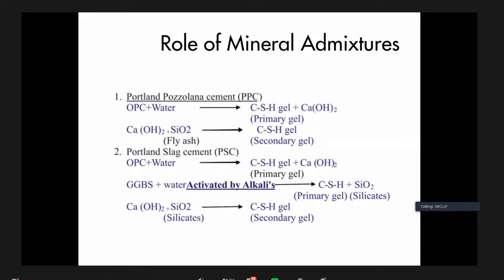Now, this secondary gel will actually replace the calcium hydroxide, and it will create a further compacted concrete. That means we will have virtually non-porous concrete, thereby making excellent quality concrete, which will not allow any moisture entrainment or any gases entrainment into the hardened concrete. And that's why in places like the UK, in the coastal areas, you are not allowed to use ordinary Portland cement concrete. You need to have a blended cement concrete.